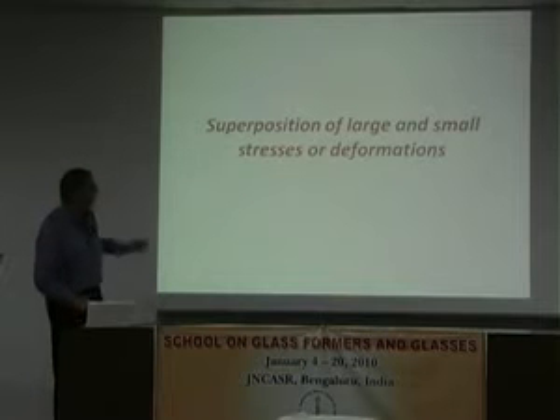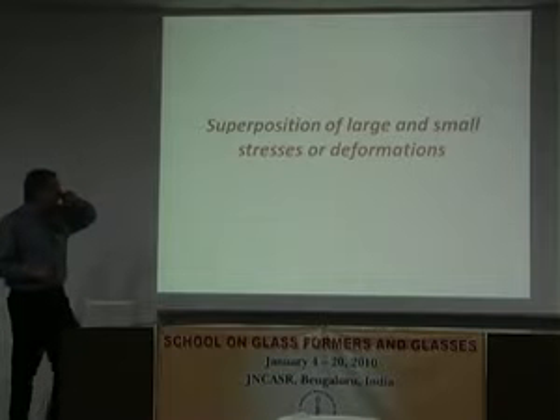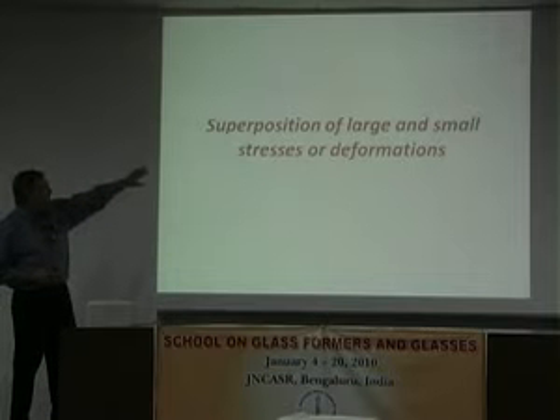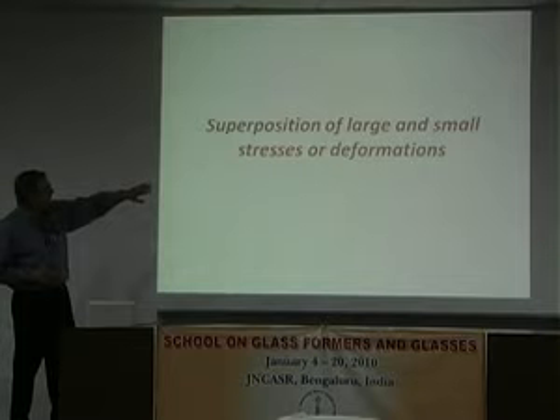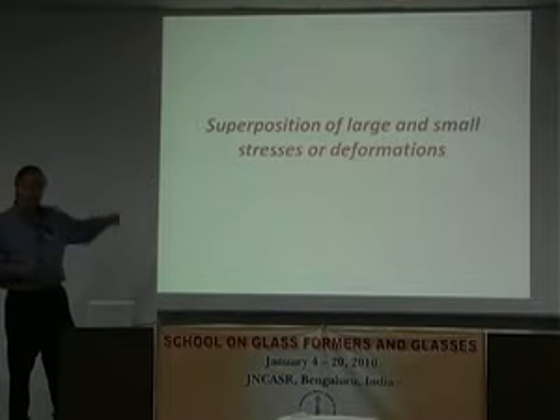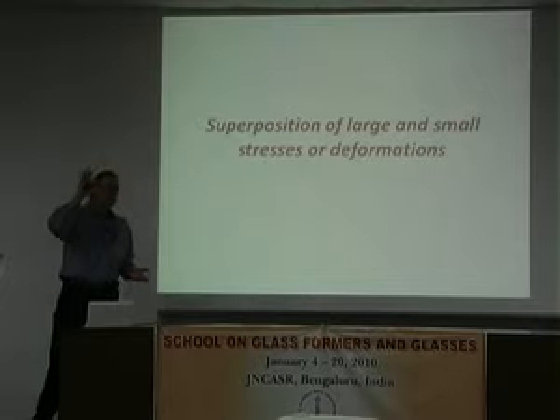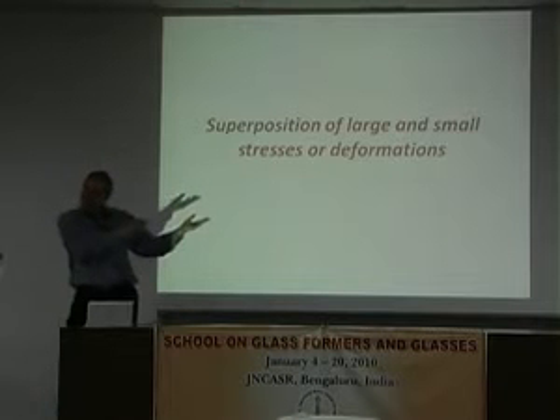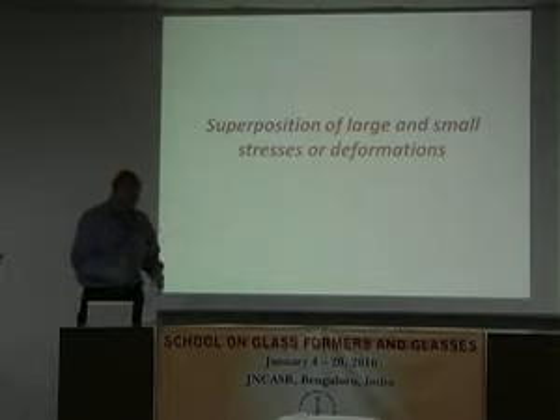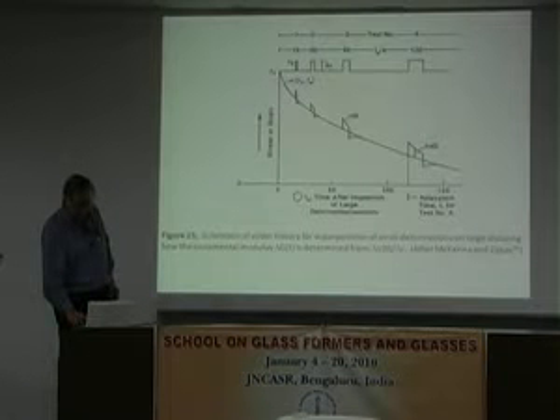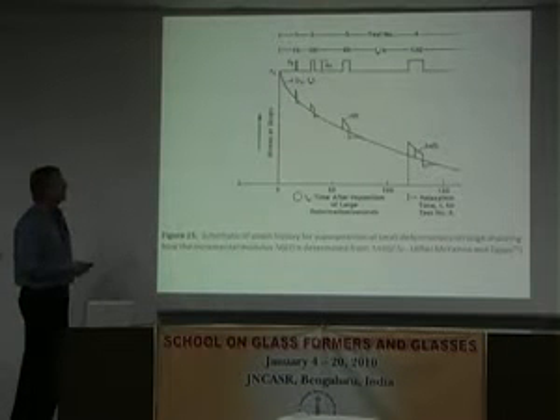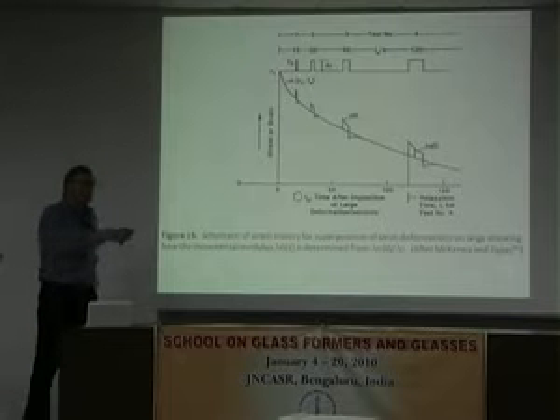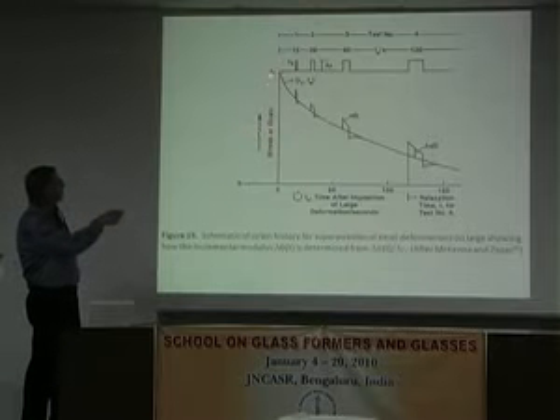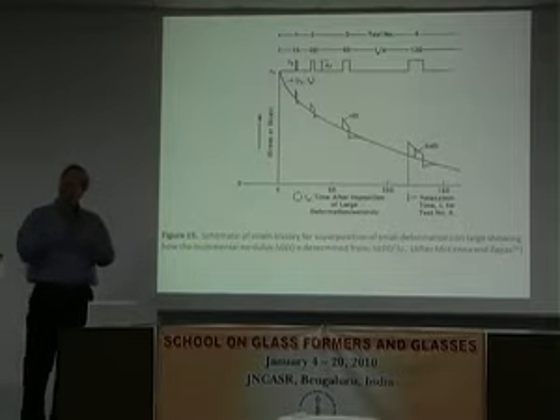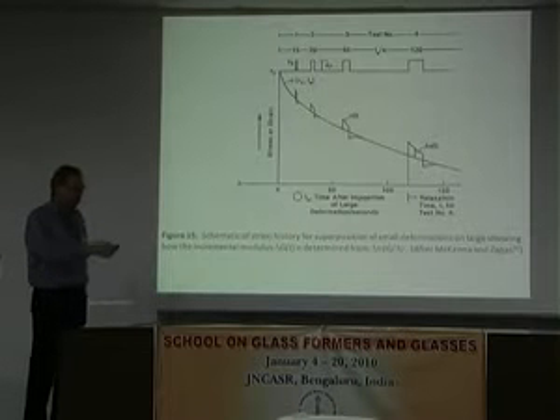Okay. Now, there were some other experiments in the literature that had to do with superposition of small deformations on top of large ones. Okay, because people are saying it's the large deformation that kicks you back towards the freshly quenched state. And they were, of course, doing experiments too, and this is the kind of experiment that got done. Some people call it a tickle experiment. So what you're going to do is you put a big deformation on the sample and hold it, so it's a large deformation stress relaxation experiment.